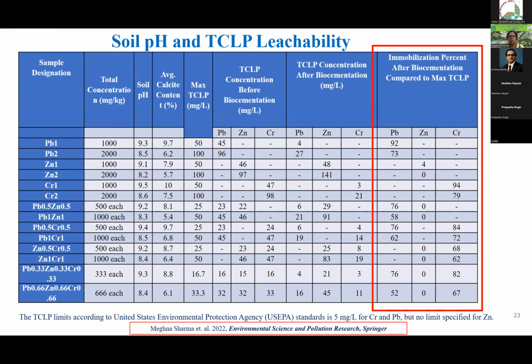And we see how much amount is leachable through the immobilized soil. So it was observed that 94% of chromium was immobilized, and 92% of lead was immobilized, but zinc was found leachable, due to smithsonite formation. Clear? This is because the pH of that solution is quite lower than 5 during the leachability testing, so zinc smithsonite won't be stable.